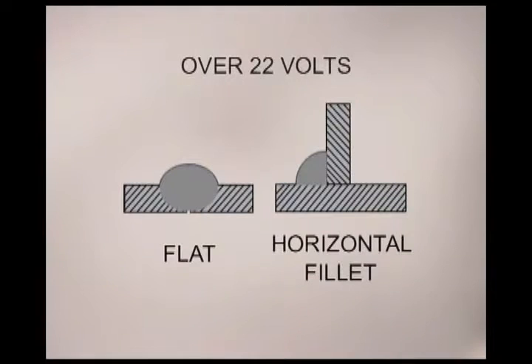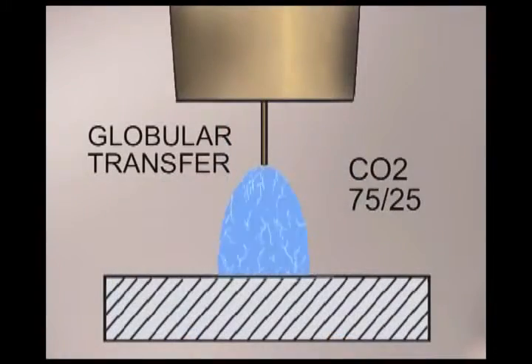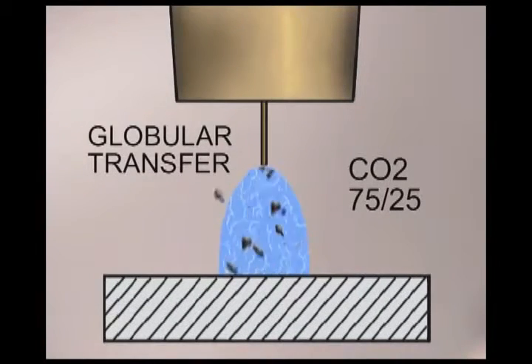Because of the amount of heat and weld deposit at these high settings, the molten weld puddle is extremely fluid, limiting globular transfer to the flat welding position or for a horizontal fillet. This will provide a strong weld at faster welding speeds, but the arc stream produced by CO2 or 75-25 allows some of the globs to escape, causing excessive weld spatter. For projects requiring a limited number of welds, this spatter can be dealt with, but in production it's undesirable because of the time it takes to clean up.